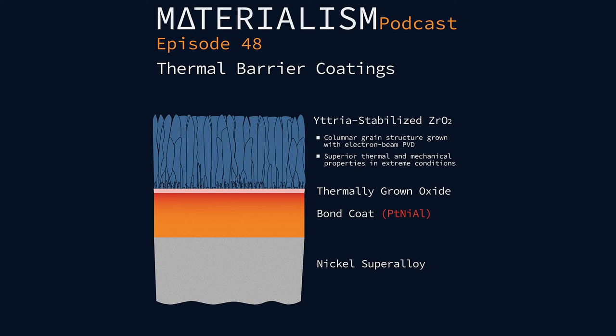Yeah, and there's a lot of work trying to look at other dopants they might be able to add to circumvent some of these problems, as well as the problem of chemical stability of the zirconia with some of the species that end up entering the turbine blades. So lots of rare earth metals like thulium, erbium, gadolinium zirconium oxide, GZO. It's a pyrochlore structure. That's one that my former advisor worked a lot on.